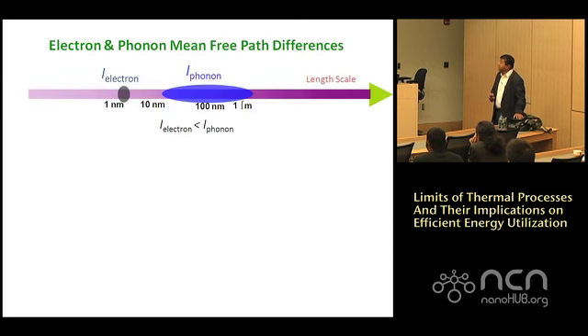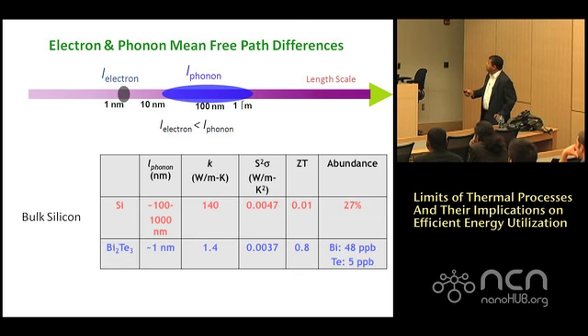This has gotten us intrigued, and we took a very different approach, which is almost blasphemous. And that is using silicon. And silicon, as I said, is a light semiconductor. The thermal conductivity is very high. The people in the semiconductor industry like that because they can dissipate heat. And I'll show you the numbers. It doesn't make sense at all, except for a few other things, that the physics can be controlled in very interesting ways. And let me explain. In silicon, or in semiconductors where the electronic mean free path is a few nanometers, and in doped silicon it is, and the phonon mean free path is several hundred nanometers, there is a length scale gap. Which means if you make your semiconductor this size, you will not change your electronic properties, but you will reduce your thermal conductivity by an order of magnitude. And that's the idea.